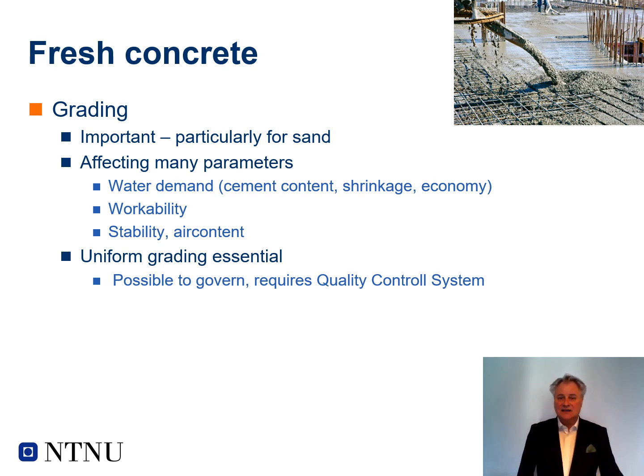And the grading will affect many parameters of the concrete. It will affect the water demand. The water demand is how much water you need to add to the concrete mix to make it flowable. And if you have to add more water, you have to add more cement, etc. to make it flowable. And if you're adding more cement, then you have a possibility of getting more shrinkage when the concrete hardens, because the cement paste is shrinking. Adding more cement will have an effect on the economy, etc. So the water demand is important, and the water demand is directly affected by the grading.